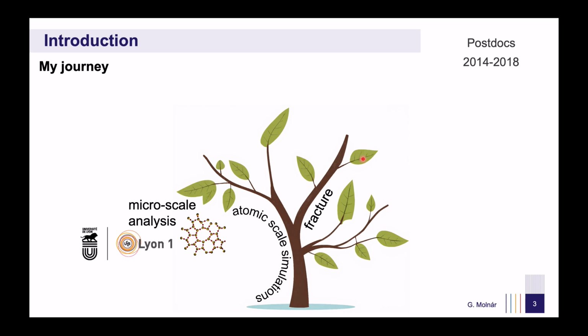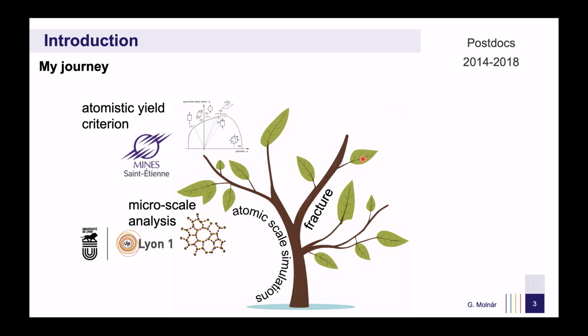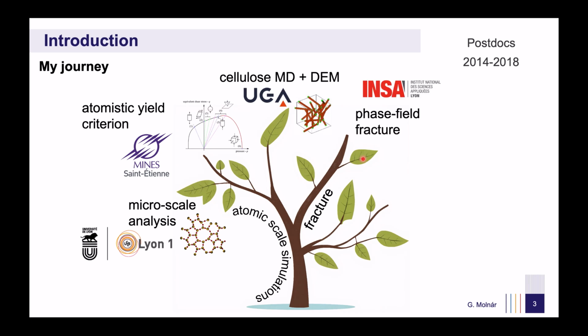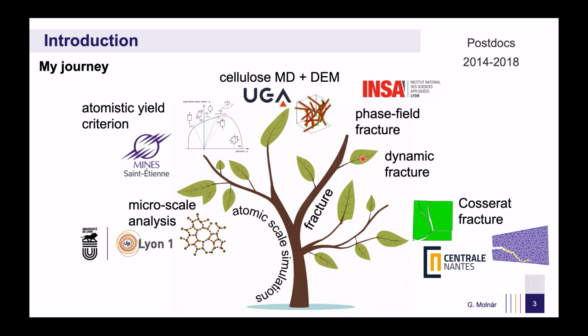Using molecular statics, we identified the microscopic events responsible for plasticity and developed a microscale inspired yield criterion for silicate glass. Next, in Saint-Étienne, I implemented this yield criterion into a finite element code and calibrated its parameters using microscale experiments. Following this, I moved to Grenoble, where I studied cellulose nanofibrils at 2 different scales, using both atomic simulations and discrete beam-like methods. Realizing that traditional yield criteria fail to account for fracture under tensile loading, I shifted my focus to the phase field model back in Lyon. I then completed my postdoc years in Nantes, working on dynamic fracture in architected materials.